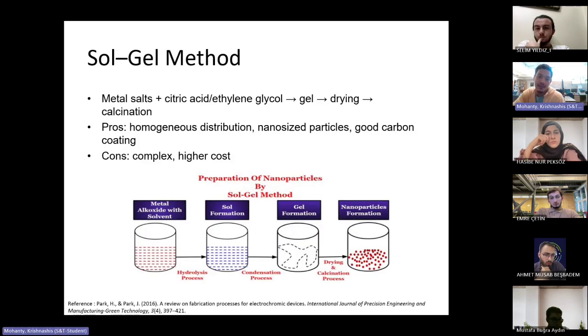Second method will be sol-gel methods, where two metal salts are dissolved in a solution in an acid and they form a gel, and then they're dried, and then they're calcined at the same temperature, around 650 to 750 degrees Celsius. The advantage is we get a more homogeneous distribution within the solution itself, because the metal salts are being dissolved in a solution, and because of that we can understand the chemistry happening within the solution, and because it's dissolving and dissipating, we'll get a more even distribution.